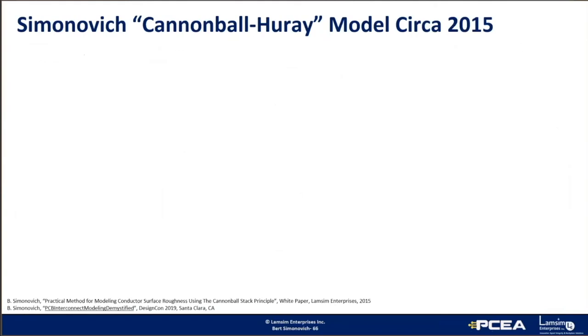So this leads to the cannonball Huray model I developed. Using the method of stacking cannonballs aboard ships, the sphere radius and base area parameters for the original Huray model can now be easily estimated solely by the roughness parameters as published in the manufacturer's data sheets.